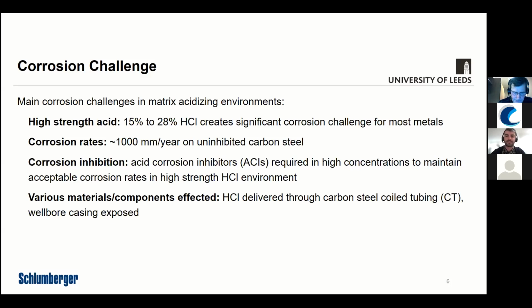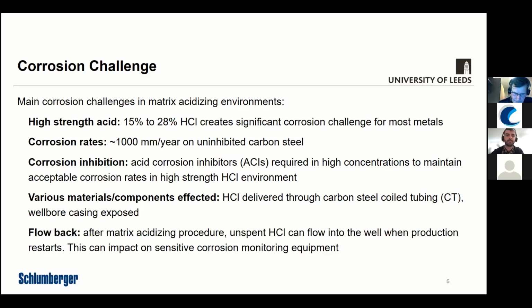Various components are affected in the process. So obviously you have to deliver the hydrochloric acid into the well, and that would be done through carbon steel coiled tubing normally. And the wellbore casing and the materials surrounding the area where the acid is injected are also exposed, and that can lead to various corrosion challenges. You've got different materials in there, and all of those materials need to be protected from the corrosive environment. And as I said, once you've completed this procedure, you can also have a flowback period, and that can impact on various other aspects of the infrastructure. To conclude, overall, it's a very corrosive environment, as you can imagine when you're using such a high-strength hydrochloric acid.